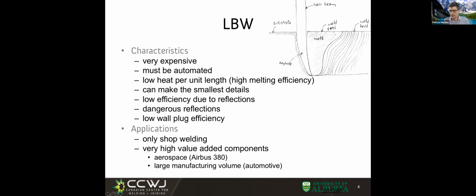I have a question: is the low heat input per unit length due to the narrow arc? The low heat input per unit length is mostly due to the high travel velocity. And there is no arc in laser welding. But it's true that the penetration of the weld can be deep and narrow, but that is more a consequence of the low heat input than a cause.